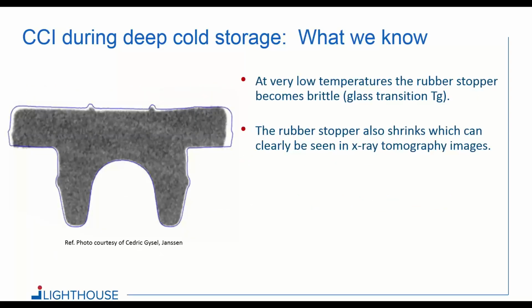I just mentioned that at very low temperatures, especially around the glass transition temperature of the rubber stopper, you start to see some physical effects happening. Number one, the rubber stopper becomes brittle. It loses its elasticity. That's the definition of a glass transition: the material under a certain temperature becomes a glass. The second thing that happens is shrinkage. The rubber stopper also shrinks, which can be clearly seen in X-ray tomography images such as this one.